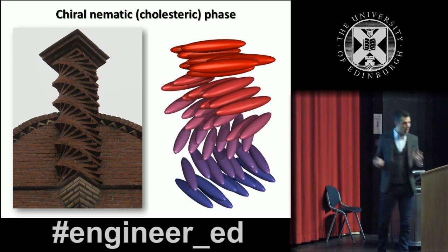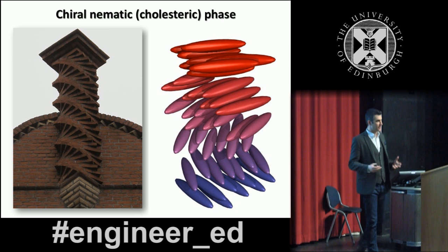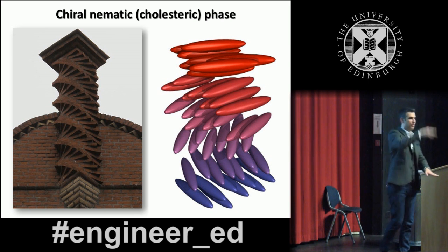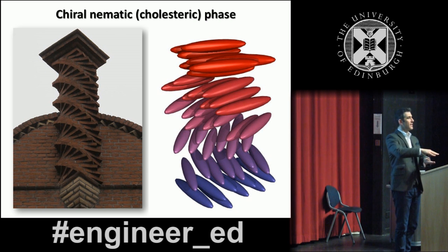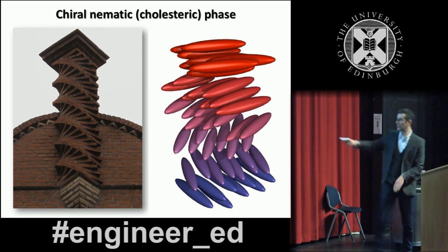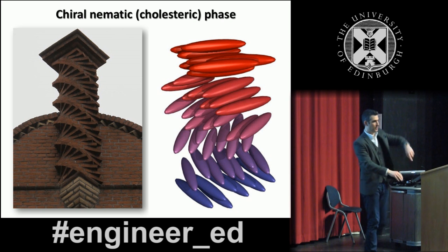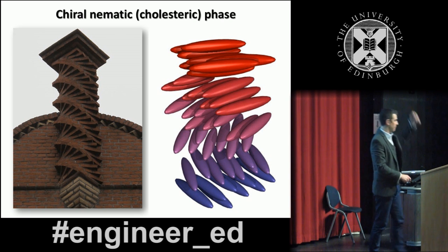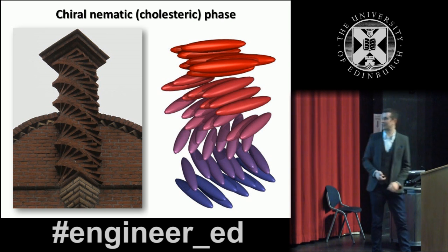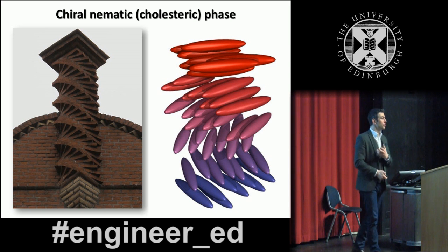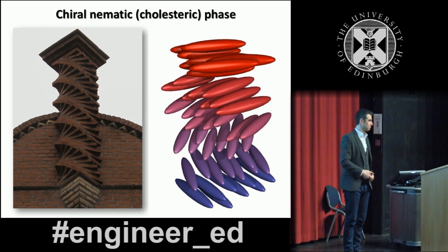What these chiral structures have, they're nematic phases, just like the fishes, but with each adjacent layer of nematic phase, the layer likes to sit at a slight angle to the previous one. So as you build up the layers, you start developing this helical twist in the director, this chiral nematic phase. And this is what's crucial to making a liquid crystal laser.